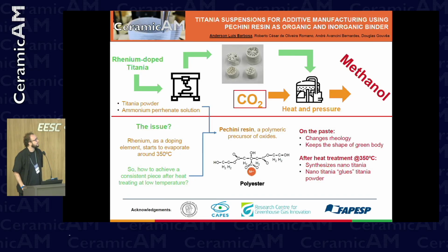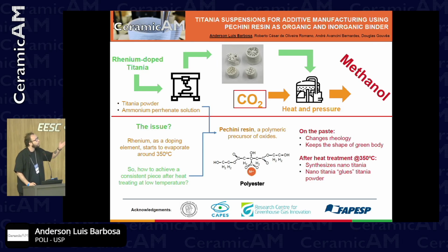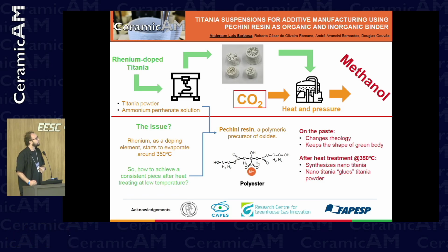I'm working on a project to convert CO2 to methanol through heat and pressure using rhenium-doped titania. My research specifically is to produce this titania paste to print the reactors through the extrusion method of direct ink writing. We are basically using titania powder in an ammonium perrhenate solution. The ammonium perrhenate is for the doping material.